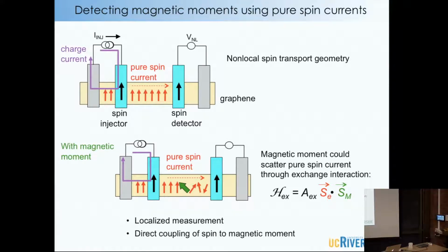What I like about this is that it's a localized measurement, so you know what you're measuring is coming from that piece of graphene, and not from somewhere else on your sample, like a sample holder or something. And also the magnetic moment is really a spin, so it's a very simple type of coupling between our electron spin and the localized moment spin, which, well, is also an electron, but, okay.